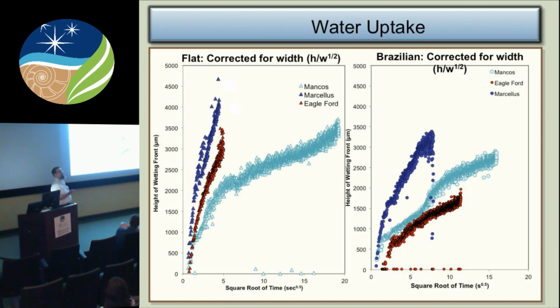I'm not going to go through this. We can go ahead and actually quantify that uptake rate. This shows uptake rates for those three materials as a function of time. As you can see again, there's also a great deal of difference in just the capillary uptake rates between these samples.